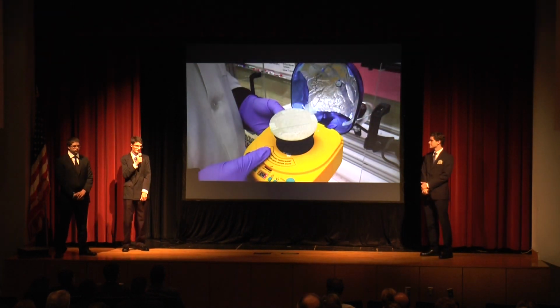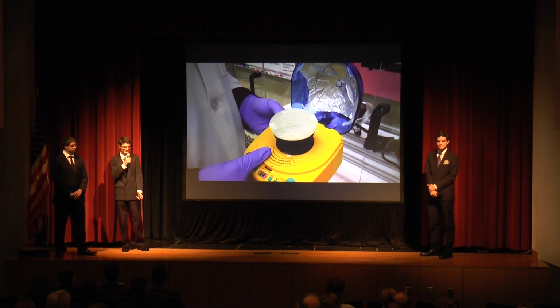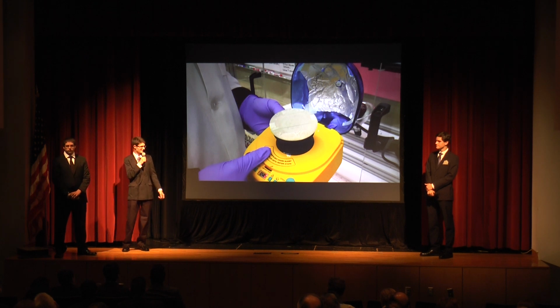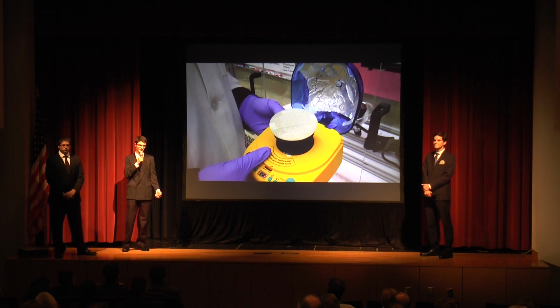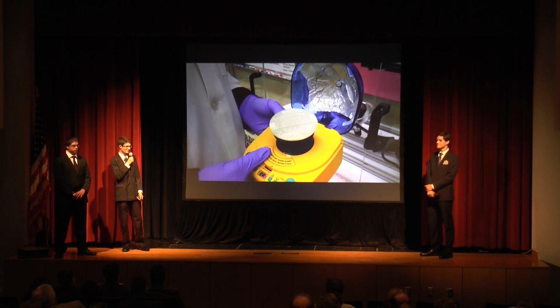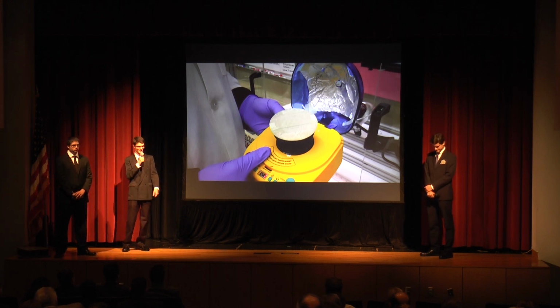As Connor mentioned a moment ago, one of the processes we use is called spin coating. This is our spin coating apparatus that was developed by the Nanotechnology research team, and in our case, it's a modified centrifuge that spins a glass slide at high RPM, and it creates a thin film of whatever material we decide to deposit. So we used it in our experiments to find an optimal blend of PEDOT and additive to find what would have the highest conductivity for future testing, as it requires little solution to use, and it gave good results.